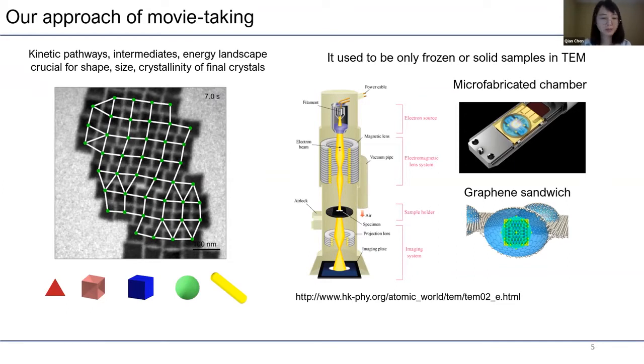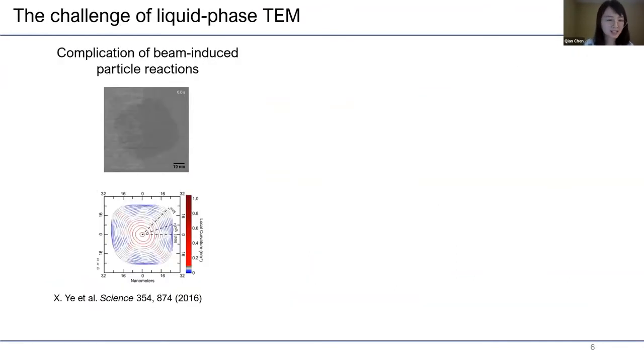The idea was perfect, but with one complication: the electron beam in TEM has high energy. It can react with nanoparticles and change their shape during liquid phase TEM imaging. This is wonderful if you want to study nanoparticle growth or corrosion dynamics, as shown in this beautiful movie here. But it can fundamentally damage the crystallization when nanoparticles behave as building blocks.